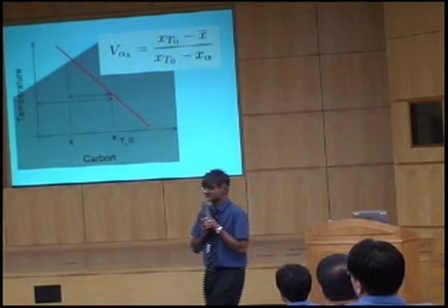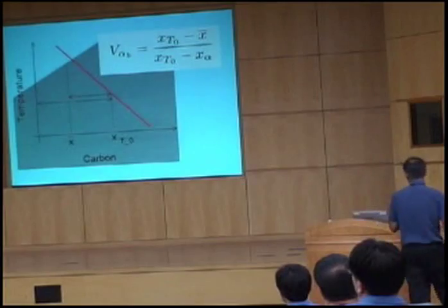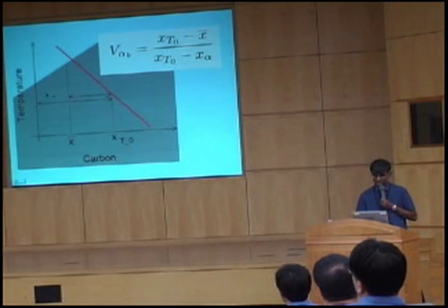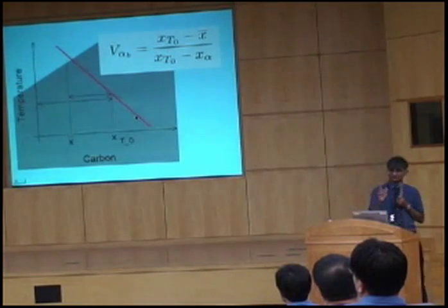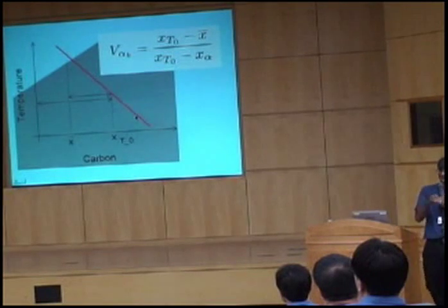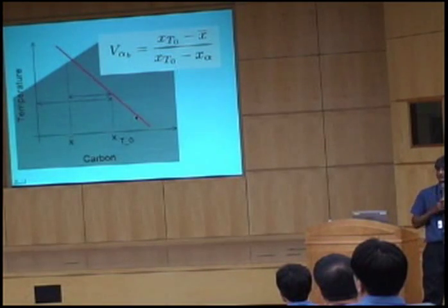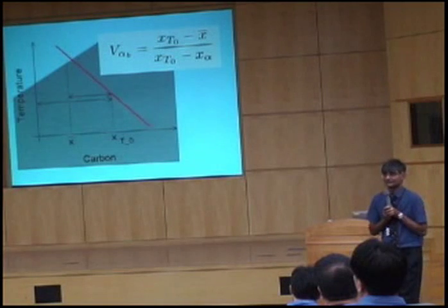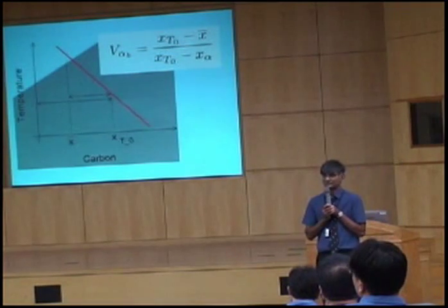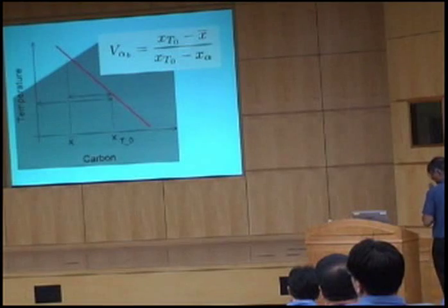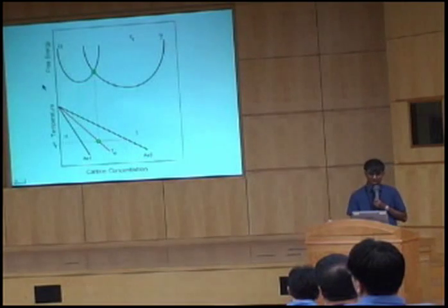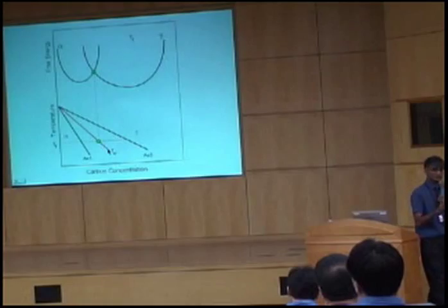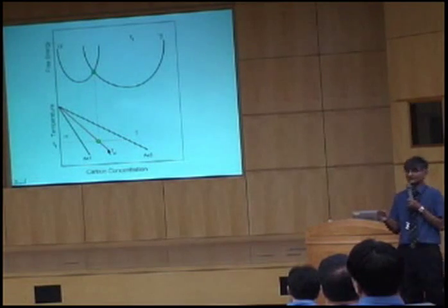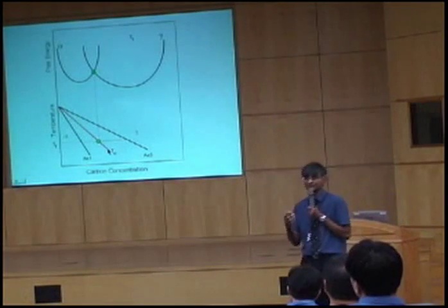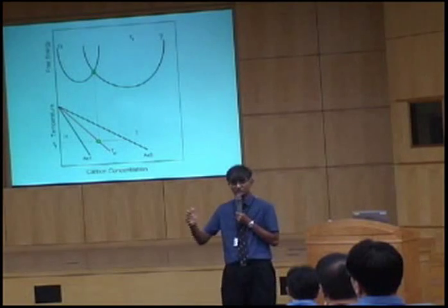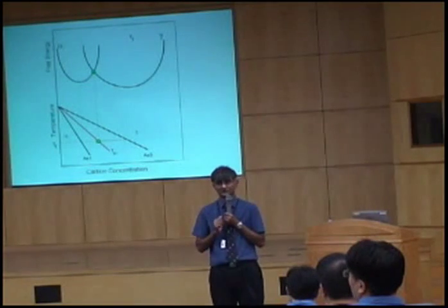Yes, decrease the temperature, because as I go down in temperature, the T0 concentration here increases. But of course, I cannot go below the martensite start temperature. Okay, and the third way. Yeah, so this T0 curve here depends on the concentrations of other elements in our material, for example manganese, nickel and so forth, and we can change its position by altering those compositions.